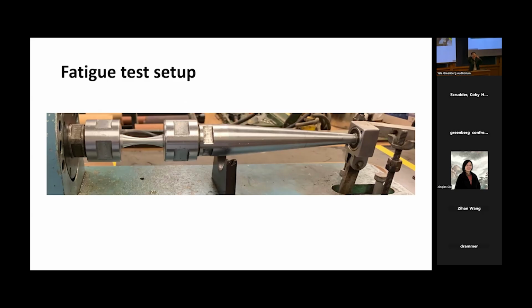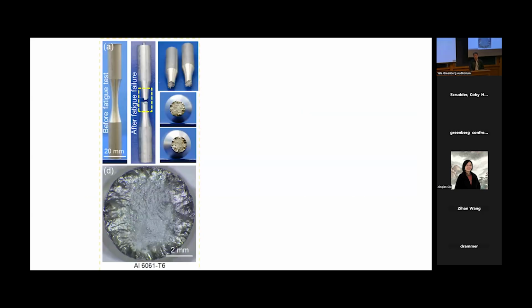So it is under tension here and compression here. When they rotate half, then the originally under tension is now under compression. So this is fully reversed cyclic testing. And we ran this overnight for a very long time until it tells us that fatigue failure occurs. Okay. The first thing we test is metal.